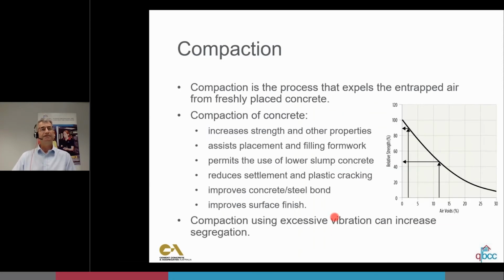So look at this graph here on the right. This shows the amount of air voids on the horizontal axis and relative strength on the vertical axis. If we order 25 MPa concrete, 100% would be your 25 MPa, and as the percentage drops, so does the final strength of the product. When the concrete comes out of the concrete agitator, it can easily have as much as 10 or 12% air. If we vibrate that concrete properly, we should get that down to 1 or 2%.